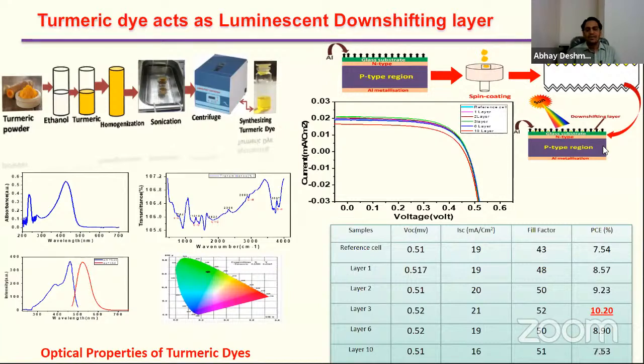Okay, and then again we tried with a cell, and you can see the reference cell has a 7.54 efficiency. For layer one, now instead of spray coating, we did it with layer by layer spin coating. Okay, so on top of a glass slide, we have taken different layers: 1 layer, 2 layer, 3 layer, 6 layer, and 10 layer.